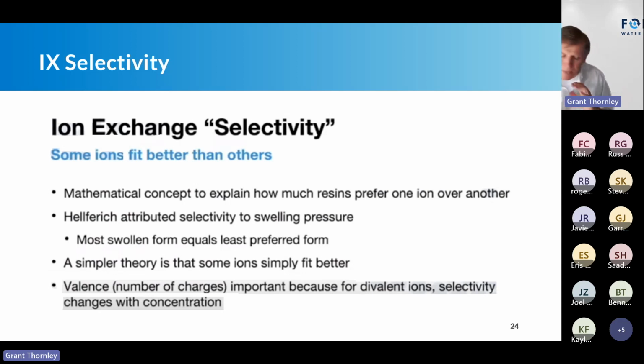The simple theory is that another concept in selectivity, not only the swollen form or the internal swelling pressure of the bead, is to think of a lock and a key. Some ions just fit better into those exchange sites than others. In some instances, a divalent will require two exchange sites to fit, and also the size and the ionic strength of that ion may preclude it from going onto the site. So this is why some ions simply fit better than others.